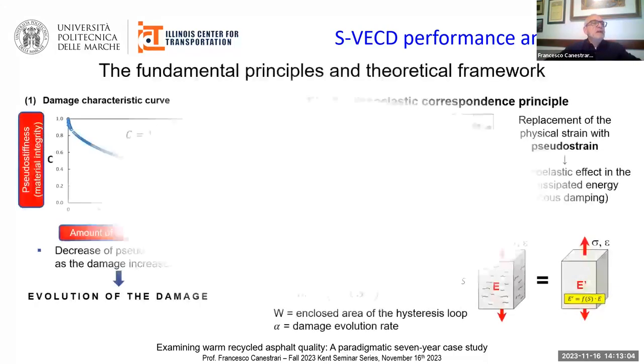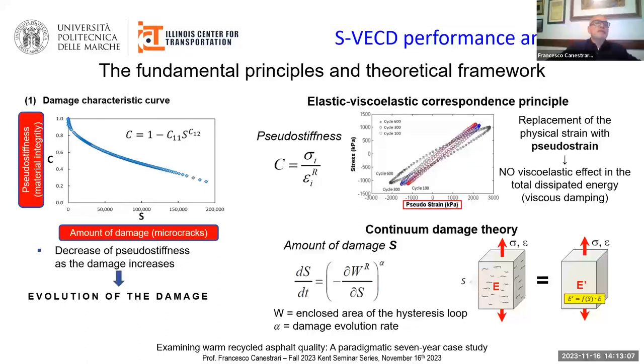We adopted also the simplified viscoelastic continuum damage analysis to compare the performance of hot and warm mixtures. Based on the elastic viscoelastic correspondence principle and on the validity of the continuum damage theory, a single characteristic curve shown on the left can be found to represent the pseudo stiffness C as a function of the damage parameter S. This curve represents the reduction in material integrity as damage grows, regardless of the applied loading conditions and temperature.